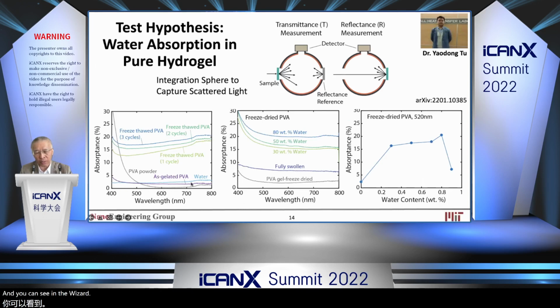And you can see in the visible spectrum, water and pure gelated polyvinyl alcohol, none of them absorb. But after you freeze dry, it becomes absorbing. In fact, if you take a dry hydrogel, that's the middle figure, and you put a little water, you don't flood the entire hydrogel with water, it becomes highly absorbing, right? And the absorbance is somewhere between 15 to 20%. So this was the first sign that we were on the right track, because a non-absorbing material became absorbing, probably because of this surface effect.